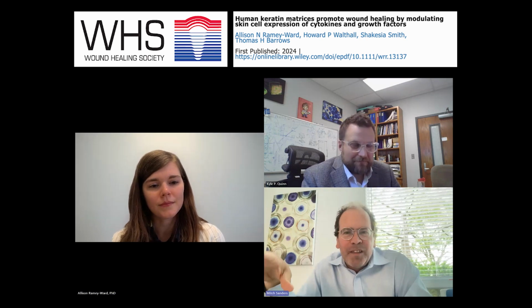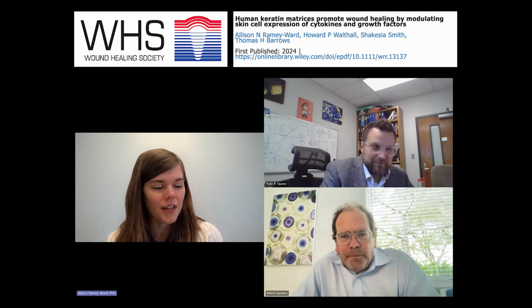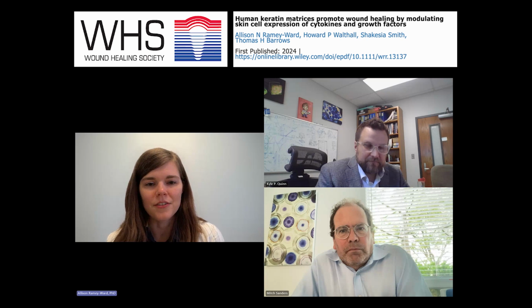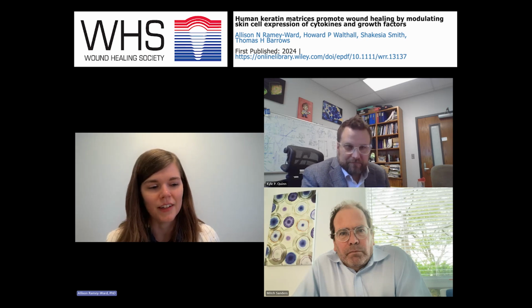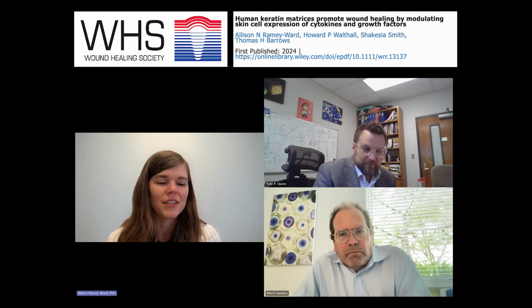Neat. Could you talk about the findings from the study? It was a really well designed, well written study. Thank you. This is a combination of some work that was done before I started, but with my background in biomaterials, I went into really characterizing the material itself. We start with basic hydrogel material science, looking at the stiffness of the material, the water content. We did a lot of proteomics, as you alluded to, to show what it's actually made of. And we do see that it's made almost entirely of keratin. It is a hydrogel, so the product itself is almost entirely water, but the parts that aren't water are almost entirely keratin. There were a few other proteins that we got hits for in that proteomics. You mentioned the calmodulin-like proteins, and those are things that we definitely want to keep digging into.